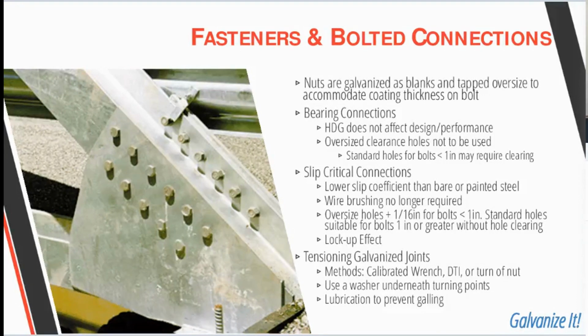For slip critical connections, hot dip galvanized surfaces have a lower slip coefficient than bare steel surfaces, blast cleaned surfaces, and often painted surfaces. But these can be painted over with a zinc-rich paint in order to increase the slip resistance significantly, or these surfaces can be masked and then provided bare or painted as well, so that you don't have galvanizing just on the faying surface.